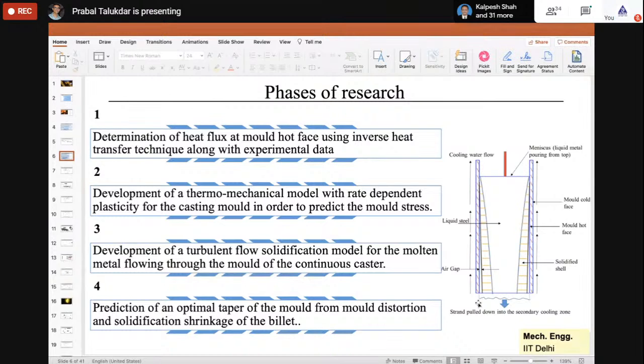Now, the first thing is, you can solve this whole problem together. You put boundary conditions outside, you solve the heat conduction equation inside the mold, then you have convection in the air gap, then you have solidification, with the momentum equation and energy equation for the molten metal. Of course, when there is a solid, you don't need the momentum equation, so you have to switch off the momentum equation. But in this portion, you need a momentum equation. There is turbulence also, so you need to use some turbulence model. All these problems need to be solved together. Again, you have a cooling water flow, which you have to model appropriately. So there are several problems together in this.